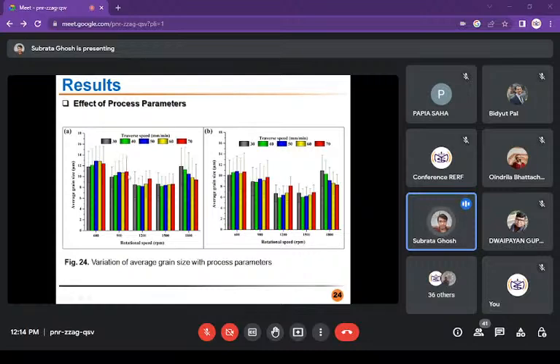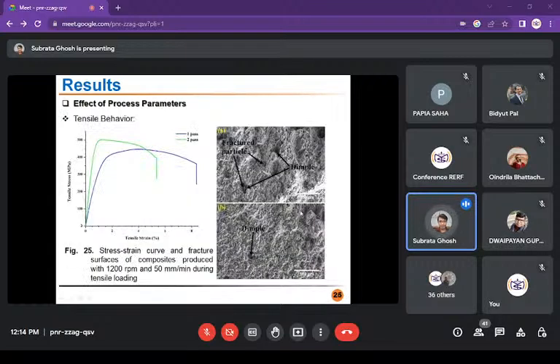This is for the first pass in figure A, and figure B is for the second pass. In the second pass you find that the average grain size is less, because the grains created in the first pass are reformed again and provide even finer grains. So the average grain size in the second pass is less. And that is the tensile behavior.